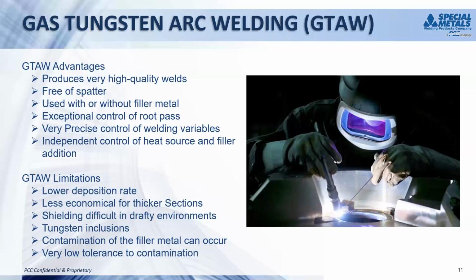The other thing is the limitations. You do need to be very protective of that shielding. Things like drafts, open windows, all that stuff can cause you some problems to temporarily lose shielding, and then you run into some problems where you could have maybe some porosity. Even if you don't get to the point of full porosity, you can get some oxygen induced in there and end up with some nickel oxide that's pretty tenacious. People that have done a lot of mechanized gas tungsten are probably familiar with the term floaters. If you lose temporary shielding, you can create some of those floaters that can be very problematic because, as Sam mentioned, they're very high temperature melting oxides that are not going to be vaporized, if you will, by the tungsten torch.